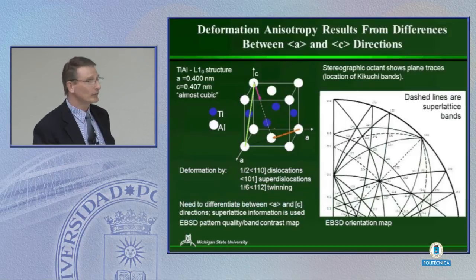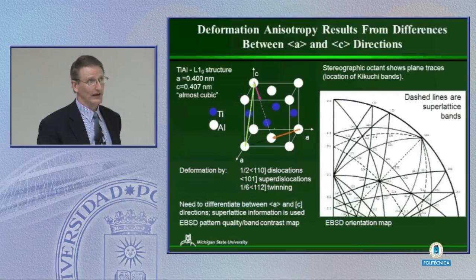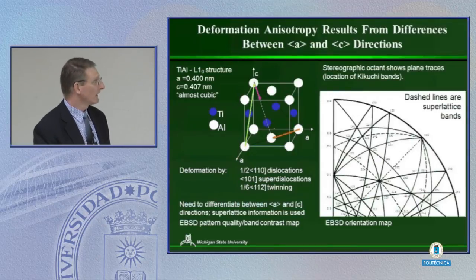And the deformation twins are kind of unique in that they occur on the typical twinning plane in FCC, the {111} planes, but there's only one twinning direction. The other two twinning directions won't be active because they would be superlattice intrinsic stacking faults with much larger Burgers vectors. And so we can get all these things going, but one of the tricky things in here,